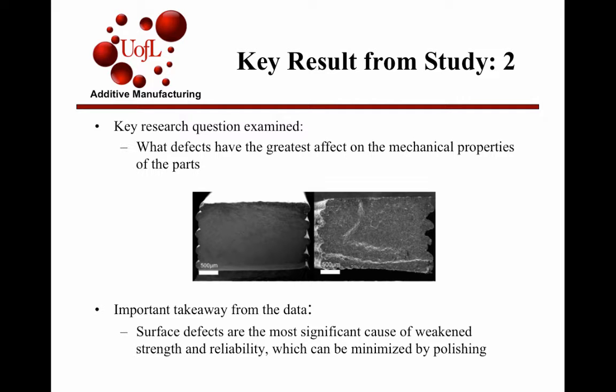Other than that, they also had bubbles within the gel extrusions themselves. To help with that, they would defoam the gel first and mix it, and that would help to mitigate those bubbles within the layers themselves. And then they also had surface pores after sintering, but they said that didn't really affect it too much, and there wasn't really too much you could actually do about that. So the biggest defect would be surface defects, and that could be minimized by polishing or using a smaller nozzle.